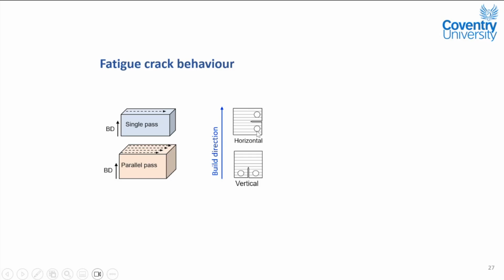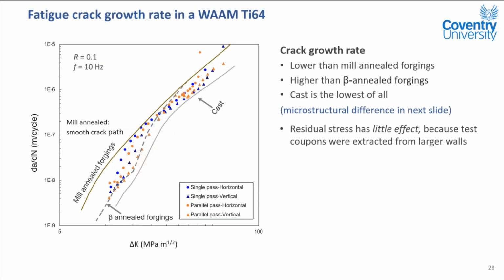And we cut many of these small compact tension specimens with 2 crack orientations. So the broader picture is like this. The colorful symbols are additively manufactured titanium. And what you're looking at is the crack growth rate, dA by dN, versus the control parameter, stress intensity factor, that takes account of the crack length and also stress applied and the geometry. So the additively manufactured material is in between the traditionally manufactured titanium.